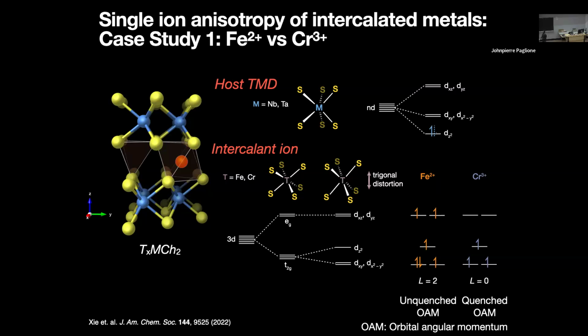So orbital angular momentum: when you have just a free ion, or all the d orbitals are degenerate, you could think of the electrons as being able to hop between all the orbitals, right? Because they're all at the same energy, and so you get whatever the maximum orbital angular momentum you might expect for that d electron count. But once you start to split them, now say for iron, you still have a large amount of orbital angular momentum. You have L equals 2 because there are 3 electrons in this x squared minus y squared pair, and so you could think of it as one of those electrons can hop between those two, and that gives you some unquenched orbital angular momentum.